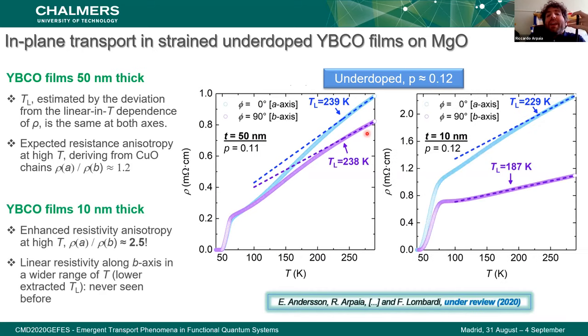If we go instead to very thin films, only 10 nanometers thick, the situation dramatically changes, because the anisotropy between A and B changes dramatically. And also, what is more surprising, the linearity changes a lot, since along the B axis, basically, we have a linear in T, which resembles the one of an optimally doped regime, even though these films here are underdoped.